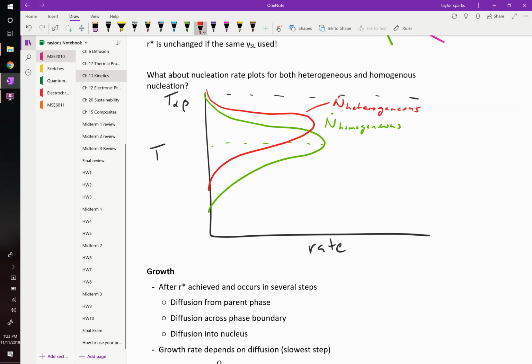Heterogeneous. Okay? You should get faster rates at a smaller amount of undercooling if you do heterogeneous nucleation. No, let me fix that. So it should look like that. All other things equal, it should be the same rate. It should just happen at a different temperature. Technically it should actually be a little bit better, because you're at a higher temperature, your diffusion's a little bit better, so it should be a little bit faster. The point is you don't have to supercool it like crazy.